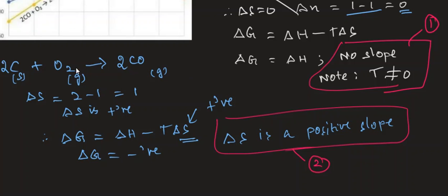As I already mentioned, only these reactions are involved in the reduction. It acts as a reducing agent. Carbon acts as a reducing agent by this reaction. How? Let us calculate delta S. So 2 moles are there, and here you have 1 mole. So 2 minus 1. I have not taken into account the solid because it is solid. So 2 minus 1 is equal to 1. So delta S is positive.